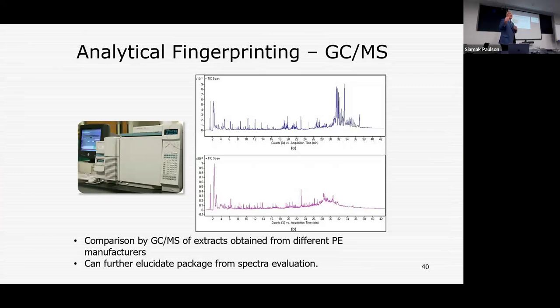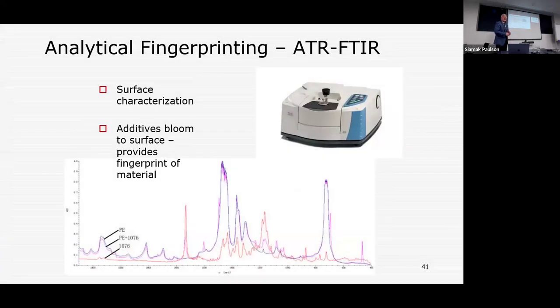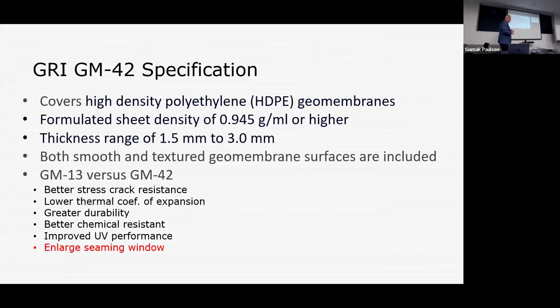In addition to that, thin films can be analyzed quite readily. They can be done in gas chromatograph mass spec, and they can also be analyzed with FTIR. So to your liking, the analysis is much easier with thin films versus the entire membrane. So you have extra forensics that are available to you. So the specification now covers high density polyethylene. Please realize 0.945 or better. Thicknesses, smooth and textured. How do we do versus GM-13?